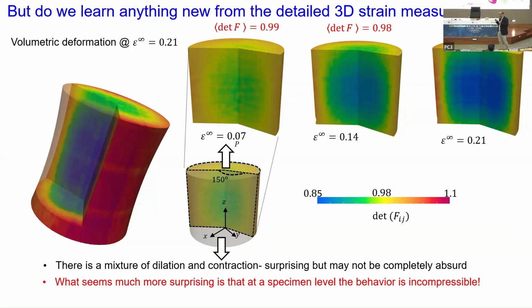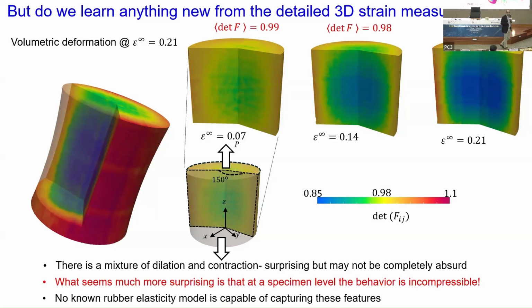But at the local level, there is enormous compressibility in this specimen. So the literature, of course, was correct that silicone rubber at the specimen level is incompressible, but at the local level, these measurements are telling you it is highly compressible. So this is very strange behavior. And of course, this was one of the first new pieces of physics that we learned. I will not go into the details of how many verification experiments we had to do to confirm that this is correct.